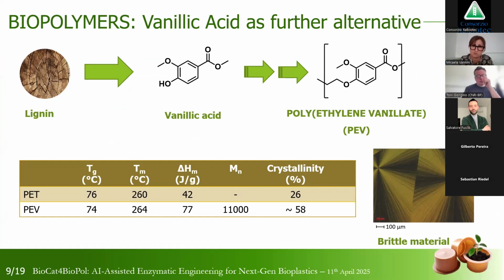This is for sure due to similarity in chemical structure, but also to similarity in the glass transition temperature and in the melting temperature, not in the crystallinity. PEV is characterized by a very, very high crystallinity, which makes the polymer very brittle.